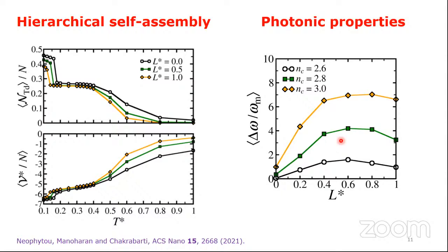We calculated the photonic band structures for randomly stacked structures. On average, we find that the photonic band gap survives, and it can be maximized with an optimal choice of L star values. Remarkably, the photonic band gap of this segmented rod-connected diamond structure is thus found to be robust to stacking faults.